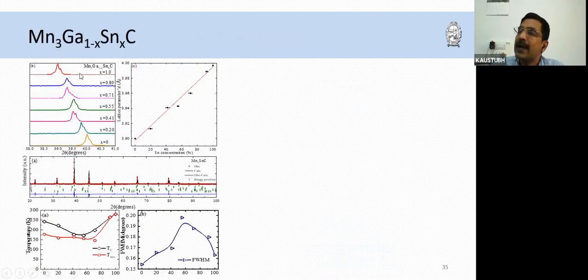So we tried to look at the full solid solution of Mn3GaC and Mn3SnC. And we can see that we can dope from x equal to 0 to x equal to 1. And we see a very good Vegard's law dependence, and the lattice constant increases very smoothly as we go from 0% tin to 100% tin in doping. All the compounds were cubic, and this was the variation of the transition temperatures, and this is the full width at half maximum of these diffraction peaks, for example. And as you can see, in the middle of the solid solution, at the in-between concentrations, the width of the peaks was much higher as compared to the two ends of the sample.